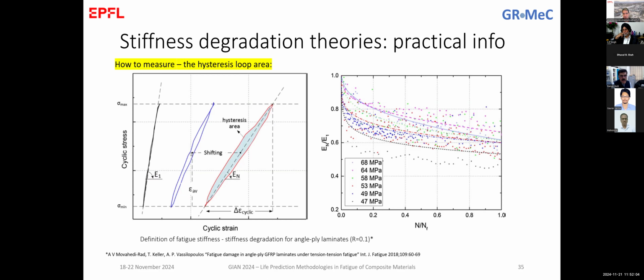As we've seen in the previous lecture from Professor Bedi, we can also estimate the creep. But if we only stick to the damage, so the stiffness drop, we can plot these values. You see also the scatter of these measurements. These are values from 6 independent specimens at different stress levels. Again, you remember the discussion that we had, that the stiffness drops more when the stress is lower. So that's why we see these black dots, for example.